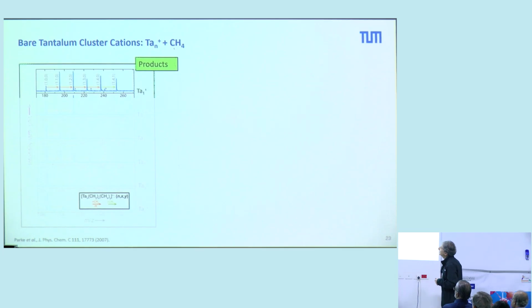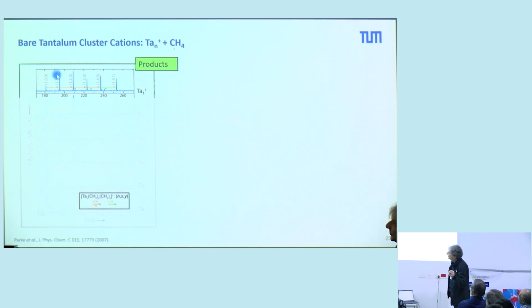Now you see here single tantalum atoms interacting with methane. And what you see if you look at the mass spec is that you can adsorb or interact with the first methane molecule and you have a dehydrogenation. That means you are producing hydrogen and you have a CH2 species adsorbed on the tantalum cluster. You can have a second one of these CH2 species, a third one, a fourth one. And then you have molecular adsorption. And so you have a distinct reactivity of these tantalum atoms which are positively charged.